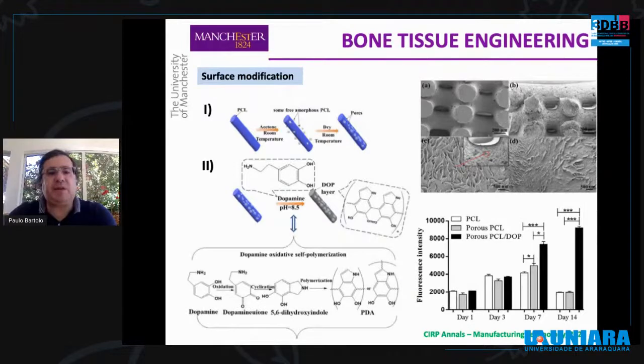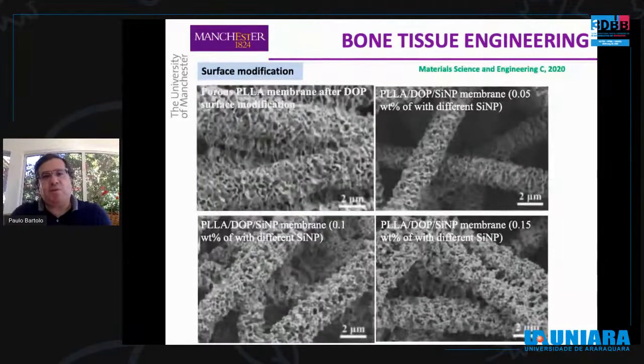The scaffolds were then doped with dopamine to increase not only the hydrophilicity of the scaffolds, but also cell adhesion and cell spreading. So here, we presented another method. The previous one was tested with polycaprolactone scaffolds produced using an extrusion-based machine. In this case, we use structures produced using electrospinning and PLLA.